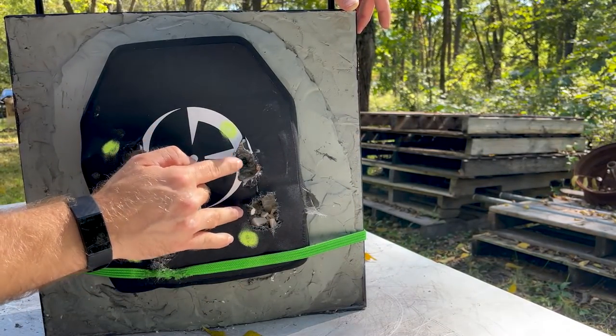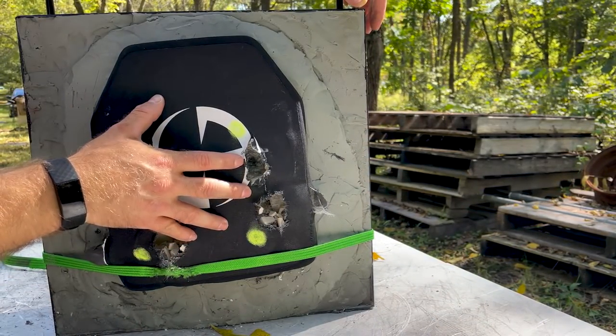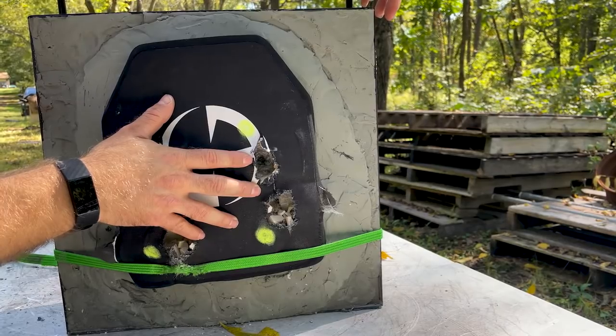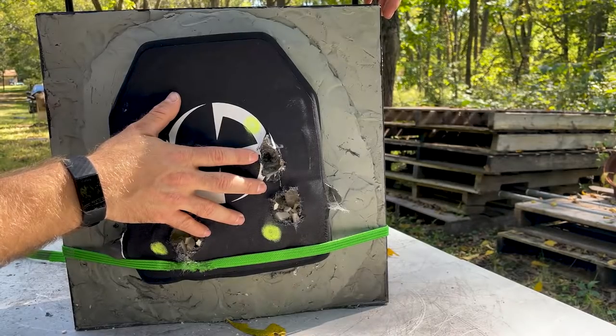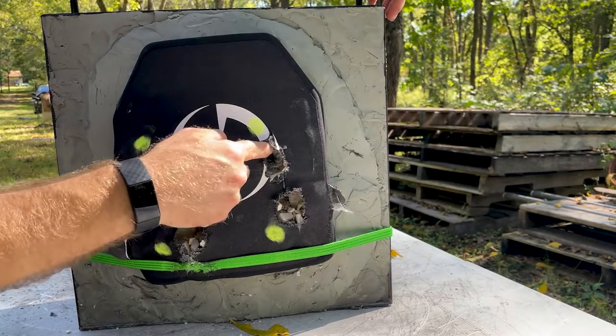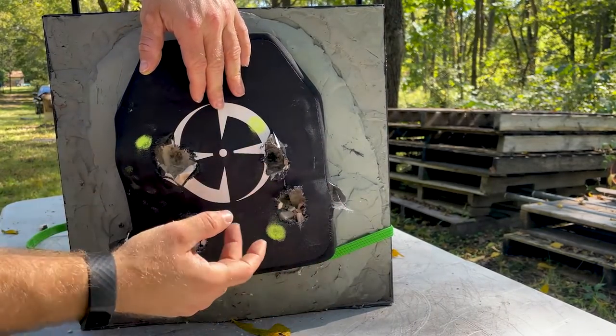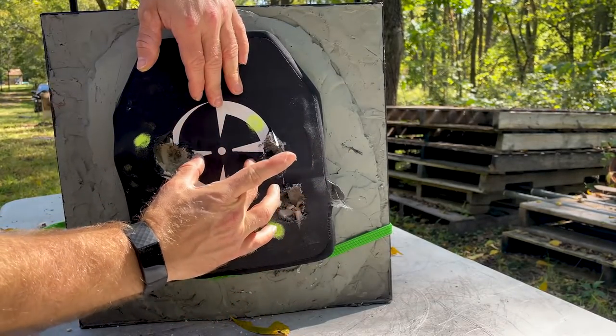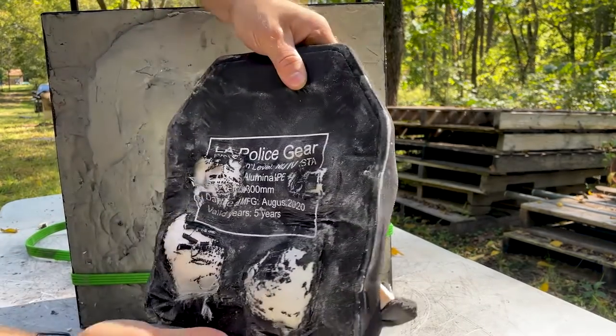This one's a little close to the action over here, but it's still more than two inches apart. Bear in mind this is an NIJ Level 4 - or upcoming RF3 - plate, and it has to stop M2 armor-piercing at 2,880 feet per second, which is usually not obtainable from a 1903 or M1 Garand or even a 26-inch 30-06 barrel. You usually have to hand-load those, and it only has to stop one shot. This is a tile array plate - there are rectangle and square tiles that make up the strike face, which helps make it somewhat multi-hit capable.